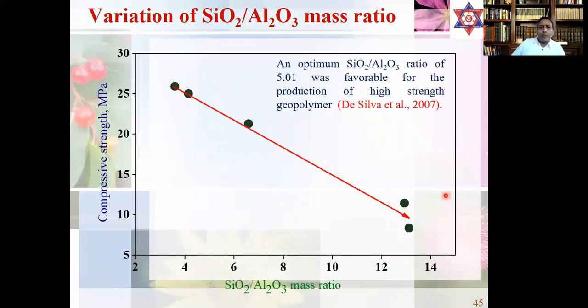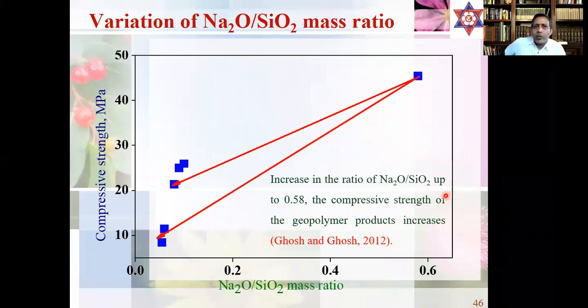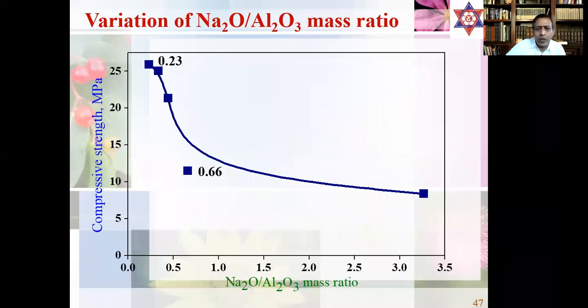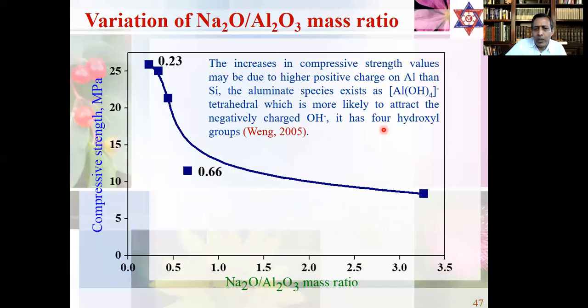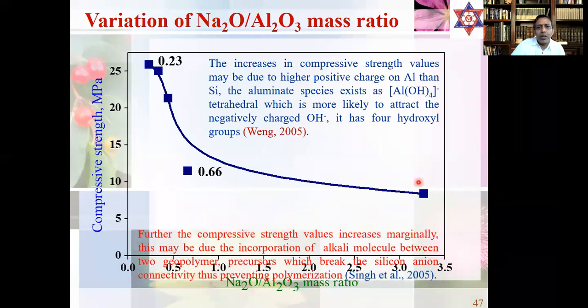So these are the variations of silica to alumina mass ratio, and what appears with the variation of Na2O to SiO2 mass ratio: with the increase of Na2O to SiO2 mass ratio, the strength keeps increasing. With the increase of Na2O to Al2O3 mass ratio, the strength gradually decreases.